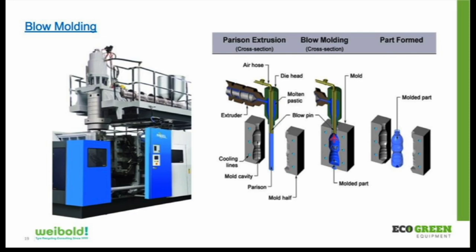So now everything's under pressure, a couple hundred, maybe 100 to 200 pounds air pressure, and it sets in there for a minute or two while the tool is cooling all around it, and then they open it up and out comes the blow molded part. Again, the key here is we're introducing just a pellet. We're not having to do a lot of special blending to get the material in.